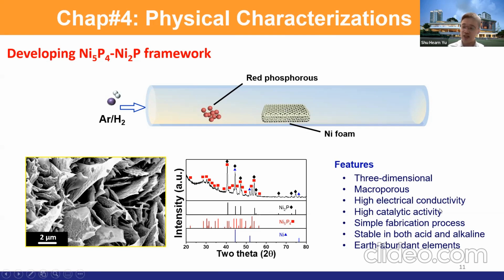Nickel phosphide has high electrical conductivity, and it has high catalytic activity. And also, more importantly, nickel phosphide is stable in both acid and alkaline. So when we apply this material, we don't need to consider the chemical stability. Because if you apply nickel sulfide, it is not stable in acid, so it will be corroded immediately if you put it in acid, even without starting the experiment. So we need to find a material that is stable in the electrolyte we want to test.